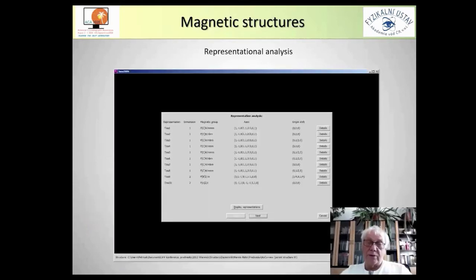Solution and refinement of a magnetic structure can be a difficult task, especially when we are using data from an unpolarized neutron diffraction experiment. Then the general function which is describing the distribution of magnetic moment in space is a vector function, but our entities are only scalar. For the solution, we can find that several magnetic space groups are making almost exactly the same result, and we have to really go through all possible symmetries. Unfortunately, even extinction rules and Laue symmetry are not enough to distinguish the correct model only from diffraction data.